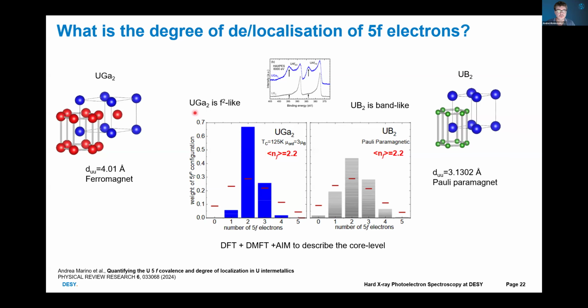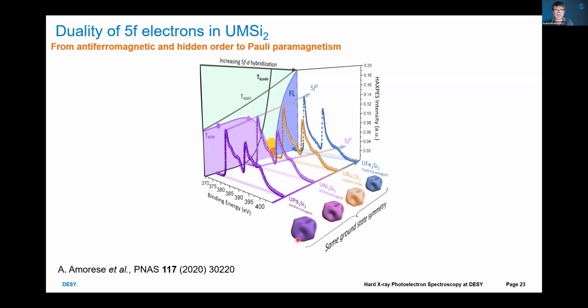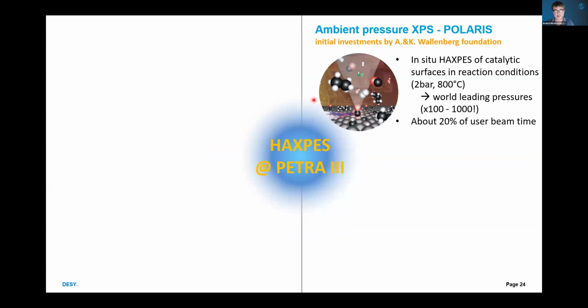And indeed, it was proven that the uranium-gallium-2 sample is F2-like with two localized electrons, and UB2 is a more itinerant and band-like material with a number of F electrons between 2 and 3. And the same group took another series of uranium compounds, namely uranium metal silicon compounds with palladium, nickel, ruthenium, and iron, which exhibit a variety of magnetic properties but have the same ground state symmetry, and based on 4F photoelectron spectra, they were able to determine the valency of 5F electrons.